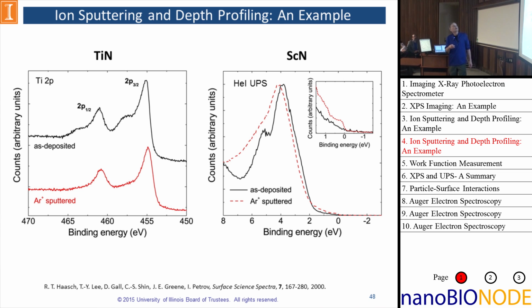Here's another example of scandium nitride. Scandium nitride happens to be a wide bandgap semiconductor, which is evidenced by this diminishing density of states up to the Fermi level. And so the black is before sputtering. After a few minutes of argon-ion sputtering, you'll notice in this red curve, we actually induced a little bit of a Fermi edge. So in this case, we're doping this material with charge carriers. And so again, changing the electronic structure of the material.